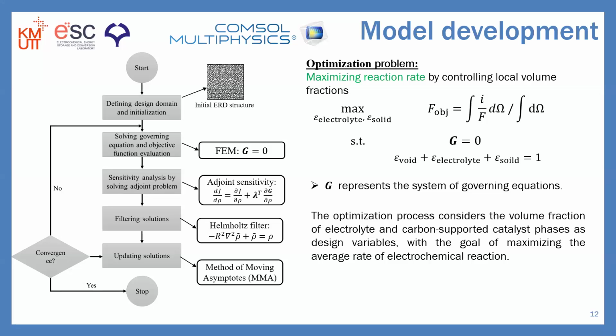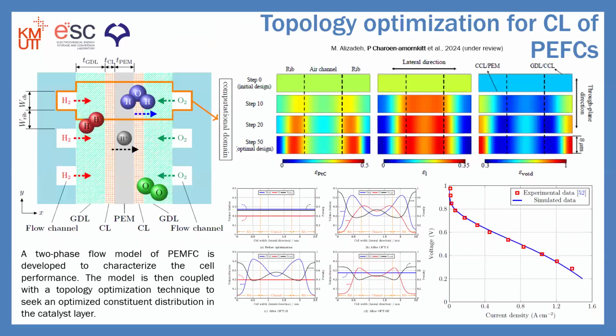We have worked on developing the coding for the optimization routine, but as the system is getting more complicated, we employ COMSOL Multiphysics to solve the governing equation and implement the optimization procedure as shown here on the left. The entire process is repeated until the convergence criterion, which in this case is the maximum number of iterations, is achieved. And here is the example for determining the electrode structure of the PEFC. We first developed a two-phase flow model of PEMFC, and then the model is coupled with the topology optimization technique to seek the optimized constituent distribution in the catalyst layer.